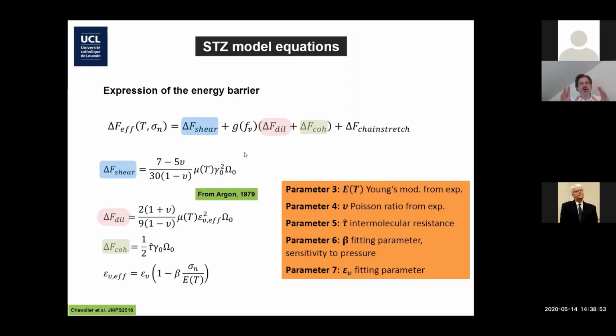Basically, for an STZ to transform, you have to accommodate shear and dilatation. And using Argon's theory, you can approximately predict the shear energy that will be associated to the shear transformation and the dilatation. This is an approximate solution, but it's nice because you know in advance what the value is. It means that in your formalism, you don't have to attempt a transformation and then go back if you have not overcome the barrier, which would make the numerical analysis more complicated.